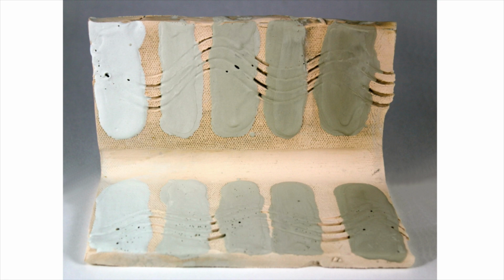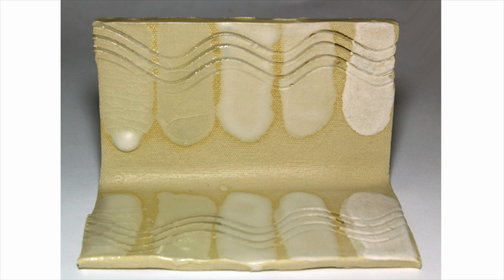Mix thoroughly and brush on a stripe of that mixture, then fire the test tile in one of your normal firings. In this test, EPK was added to produce a matte glaze. So then you assess the fired tile, showing how the influence ingredient, in this case EPK, affects the base glaze, making it go from a glossy to a matte glaze.